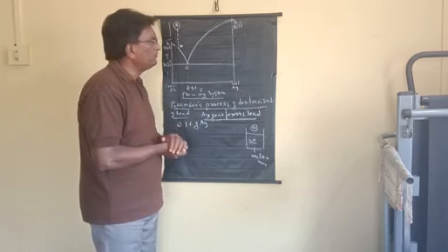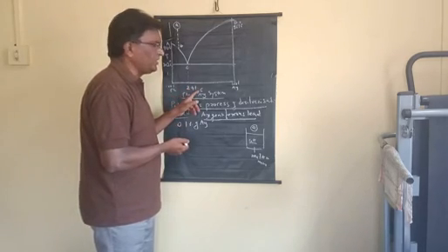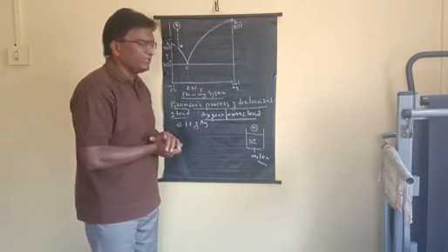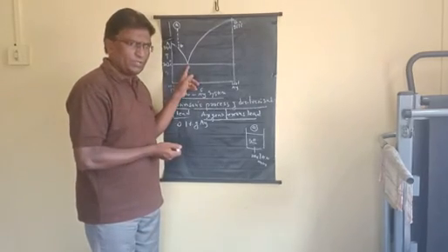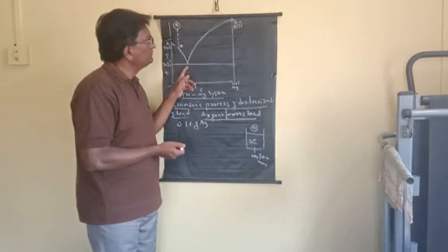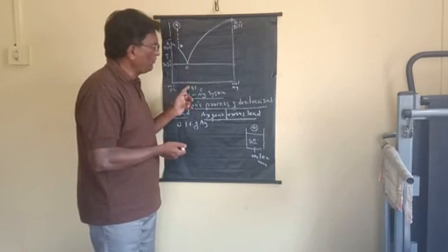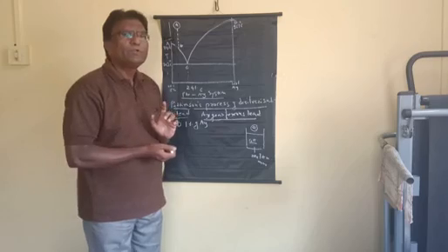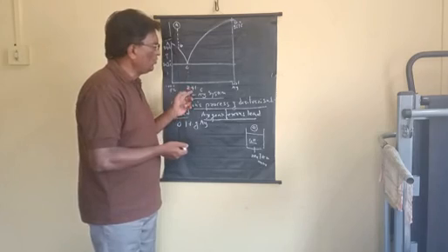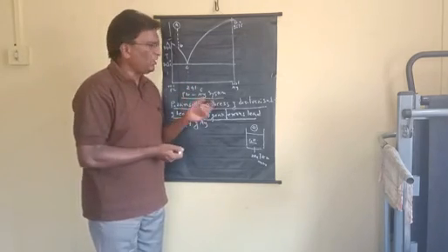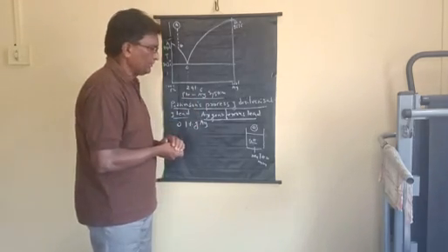and that will continue until a concentration of 2.4% of Ag is reached. That means point C is reached. At point C, the new phase will separate out, that is Ag, and therefore after repeated cooling of this particular mass, we can obtain the 2.4% of silver, and this is the Pattinson process of desilverization of lead.